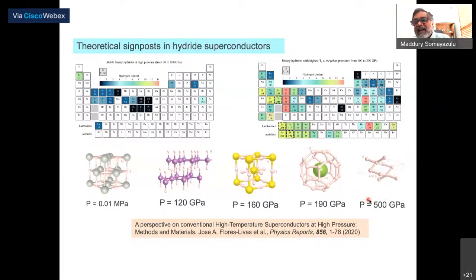And of course, at the end, I put what would be the metallic hydrogen at about 400 or 500 GPa, again, based on theoretical simulations. I mean, there has been no structural study so far where you can see the configuration of hydrogens. So obviously, from a structural concept, you can understand that this is what is driving the higher and higher transition temperatures: the propensity to form these clathrate-like structures with the hydrogens in there.